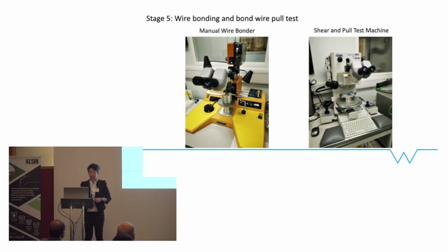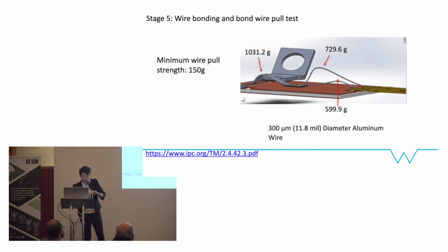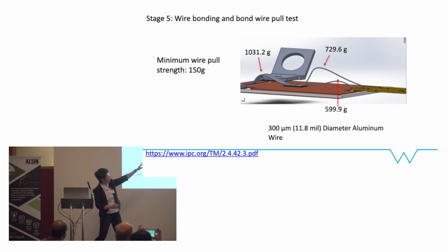After that, what we did is a wire bonding and bond pull test. On the left-hand side is our half-manual wire bonder, and on the right-hand side is the Dage 4000. For the aluminum wire with 300 micrometer diameter, the minimum wire pull strength should be 150 grams. And this figure shows our testing results. And apparently they all pass, they are much higher than this value, so the tests are passed.